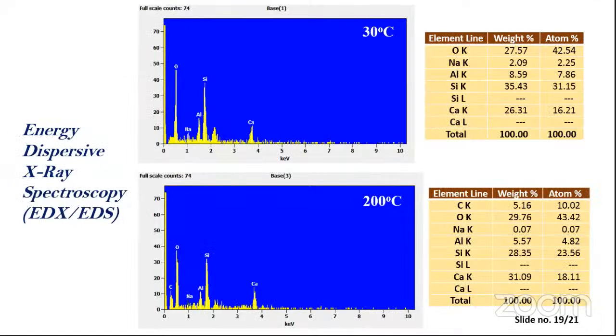And from the EDX analysis, we can see the chemical compositions here. Silicon is there, calcium is there, and I have shown only two temperatures, at 30 degrees and at 200 degrees. The percentage weight and atomic percentage weight vary with the increasing temperature. Some elements are decreasing, some elements are increasing here. If you observe on the right side, oxygen is 27% at 30 degrees centigrade, and the same is 29% at 200 degrees centigrade. Whereas aluminum oxide is 8.59 here, and here it is 5.57. So some elements are increasing with temperature and some are decreasing. That is also one reason for deterioration of the mechanical properties of concrete.